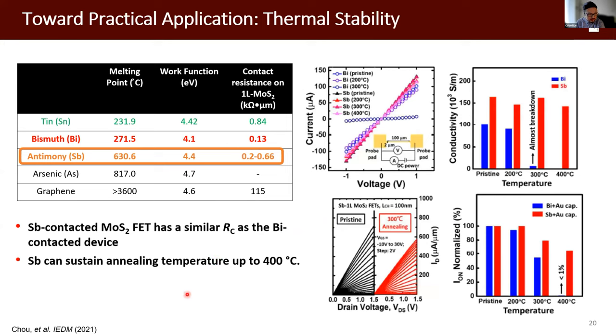So later, our colleague at TSMC developed another semi-metal, antimony, in the same chemical group. This antimony has a much higher melting point. So we measured a fabricated device based on it. And as we can see, antimony devices can survive different annealing temperature up to 400 degrees Celsius, whereas for bismuth contacts, the device performance is completely gone after 300 degrees Celsius annealing.